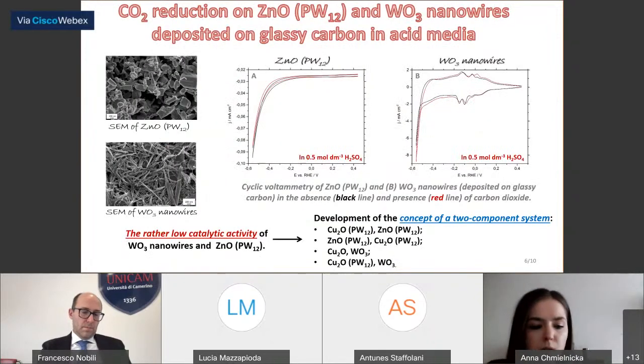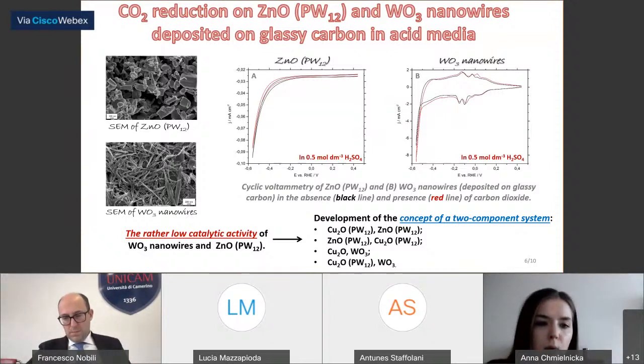So we propose the utilization of a copper-type system together with metal oxides, particularly mixed metal oxide, in acid media. On this slide, we have CO2 reduction of modified zinc oxide and tungsten oxide nanowires. In graph B, we see typical reducing tungsten oxide peaks, indicating the formation of so-called tungsten bronzes. We have rather low catalytic activity of tungsten oxide nanowires and modified zinc oxides. So we developed a concept of two-component systems, which are given on the slide, and I will discuss them in the next slides.